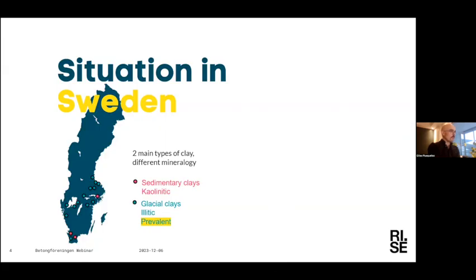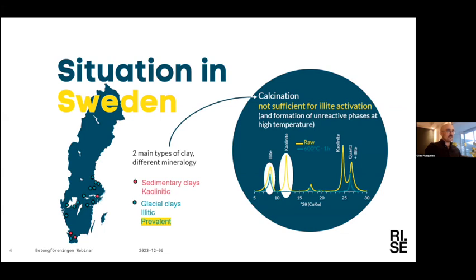A few years back, we made an inventory of what we have in the country, and we received samples from different parts, and we categorized them according to their mineralogy. We saw that we have mainly two types of clay in the country. The pink dots here show where we have the kaolinitic clays, and the blue dots correspond to the illitic clays. As is clear, we mostly have illitic clays in Sweden, which was not what we hoped for, because kaolinitic clays are really easy to activate and use with cement. For illitic clays, we cannot just calcine them and mix them with cement. That will not work that well.